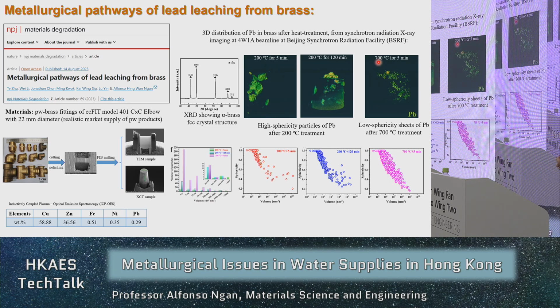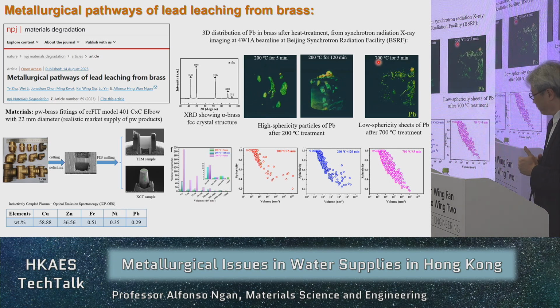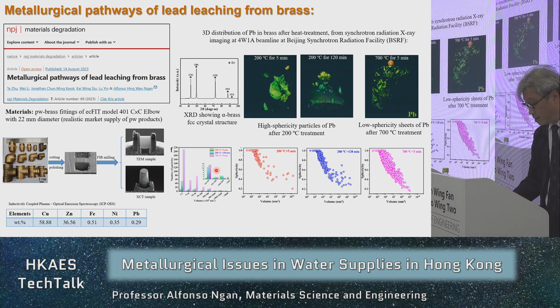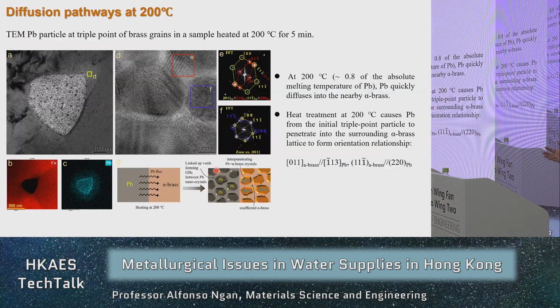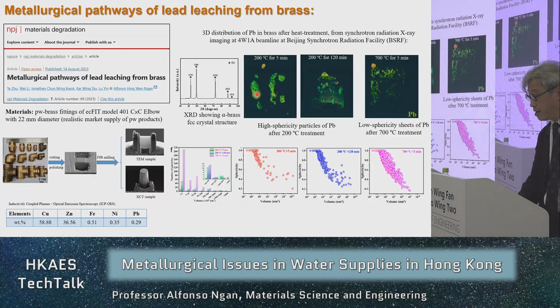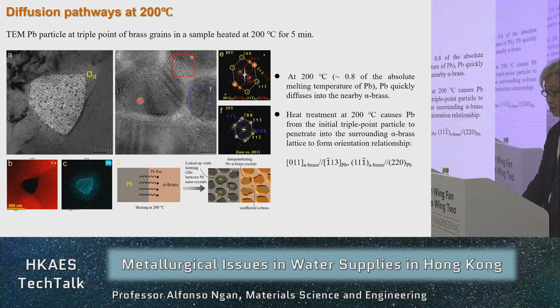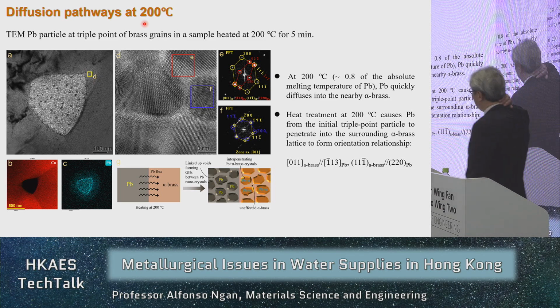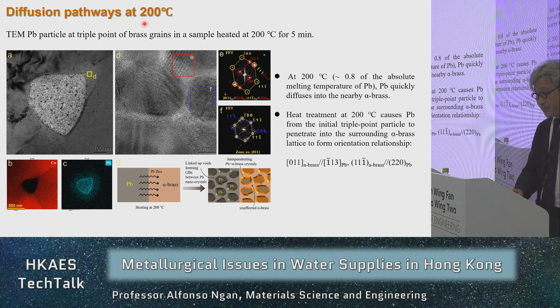So the sphericity reduces. At the lower heating temperature, let's say the soldering condition, you have these rounded particles, and a lot of them are at triple points between grains, the so-called triple point grain boundary junctions. Okay, after heating at 200 degrees Celsius, the lead would not melt at this temperature, right? Lead would melt at about 300-something degrees Celsius. So the lead is still solid, okay?